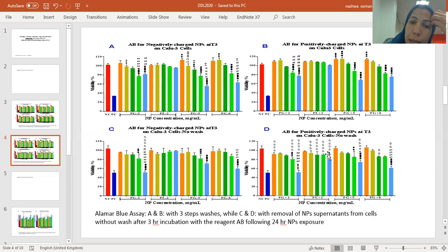But here, that is saying either the nanoparticle still on the surface of the monolayer is still exerting a cytotoxic effect, or there is an interference between the nanoparticle, the cell and the reagent, making the reagent uptake less. What you can see here is higher cytotoxicity compared to this. They are not even comparable. This could be applied by researchers, and we see many examples of them in the literature, where there can be a false claim of a higher cytotoxicity while it is not.